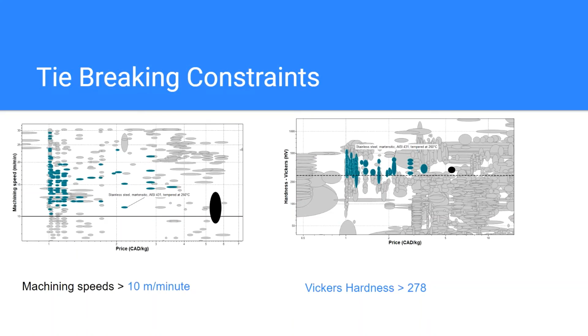Several other limiting conditions were applied to further reduce the number of possible materials. Since the threads of the bolts are commonly cut, all materials with machining speeds less than 10 meters per minute were eliminated. The threads of the bolts should also have good wear resistance, so all materials with Vickers hardness less than 278 were removed. 278 Vickers hardness was chosen because it is the minimum range of hardness specified for a SAE grade 5 bolt.